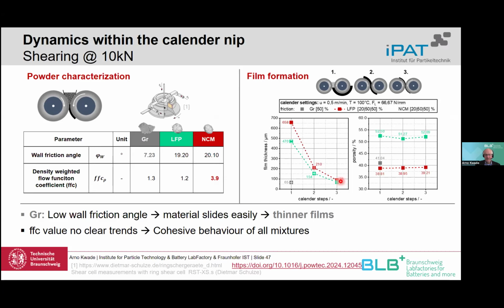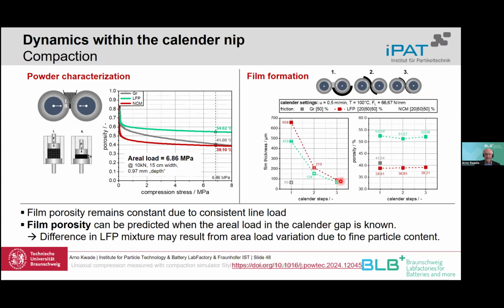A much better measure is the uniaxial compression. And what I want to show here very shortly is that with this measurement, you can predict almost, if you know the line load in the calendaring machine, what is later on the porosity of your layer.